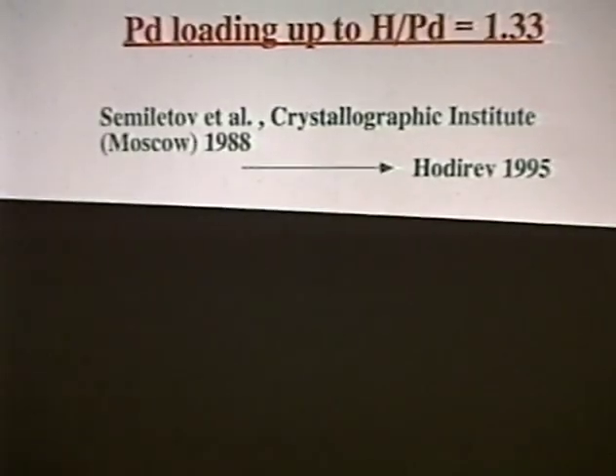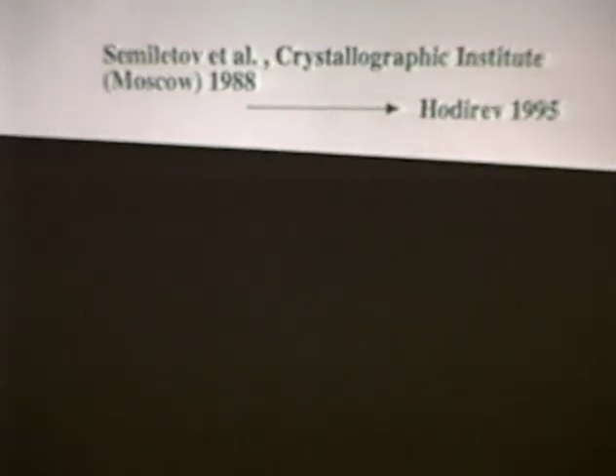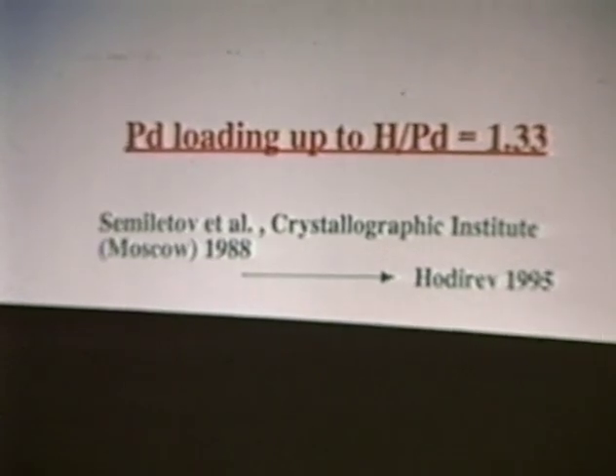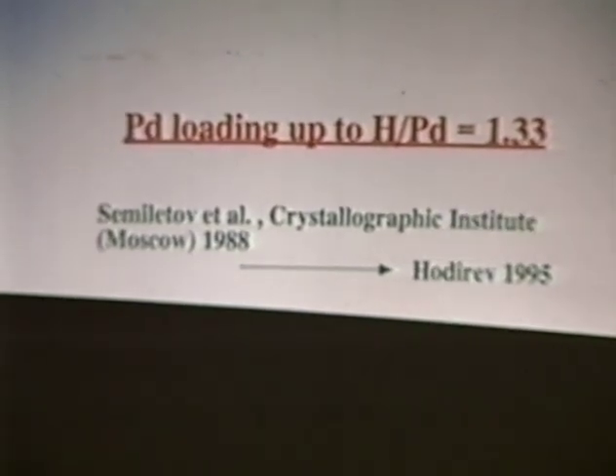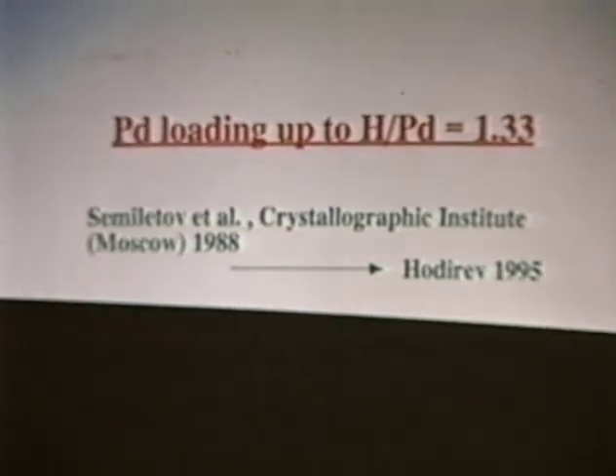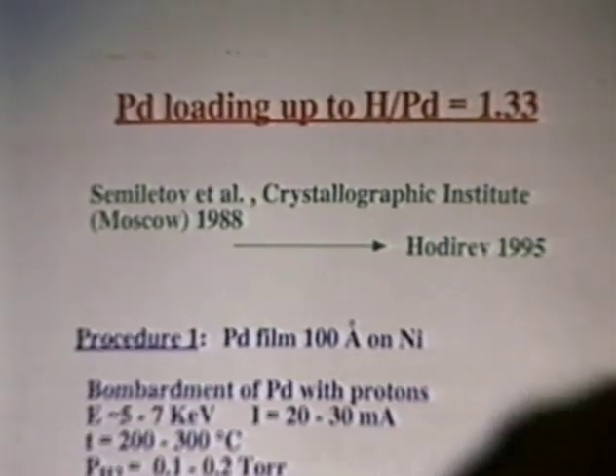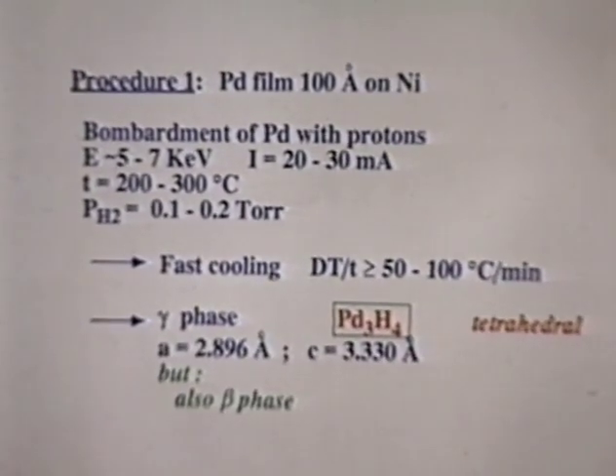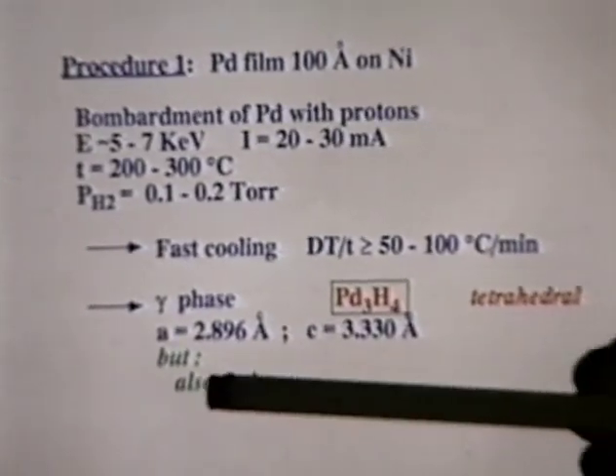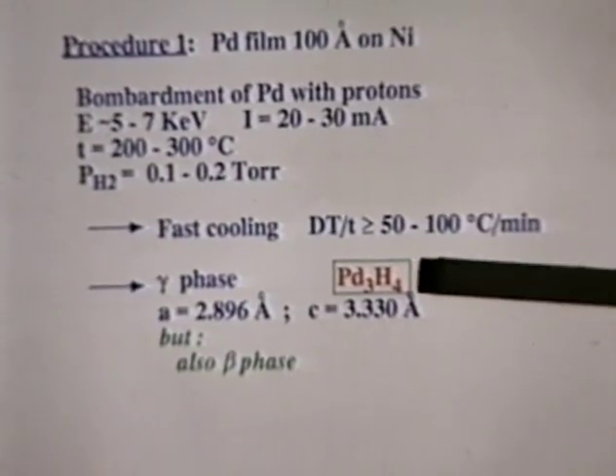So now, how to overcome this problem of the loading? We went back to a paper from Semiletov et al. in Moscow, in '88, which claimed to have achieved 1.33 loading, and we have tried to reproduce it together with Hodirev from Kazan, in February '95, with 2 different procedures. The first procedure has not perfect results.